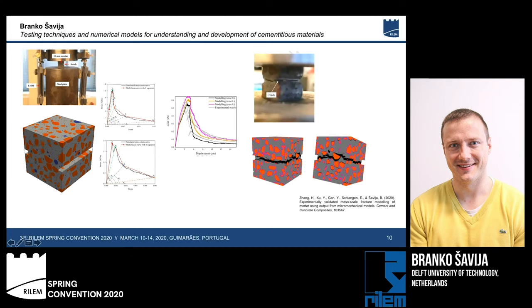So what we have actually done is we have started from the microscale. We have not used any calibration or fitting, and we don't use any empirical parameters. And we're still able to predict, with this multi-scale modeling, computational and experimental approach, the global behavior of our specimen. So with this, we can then play with the parameters at the microscale with different additives and see how that will affect the behavior of our mortar.